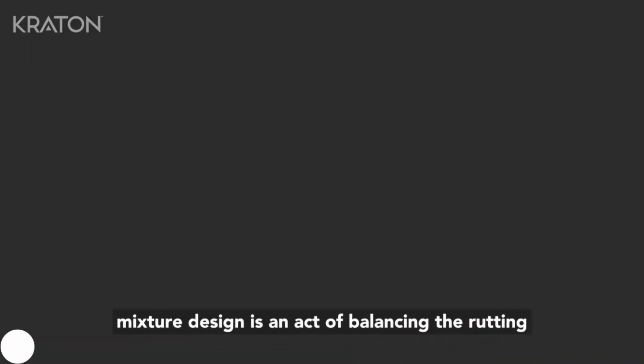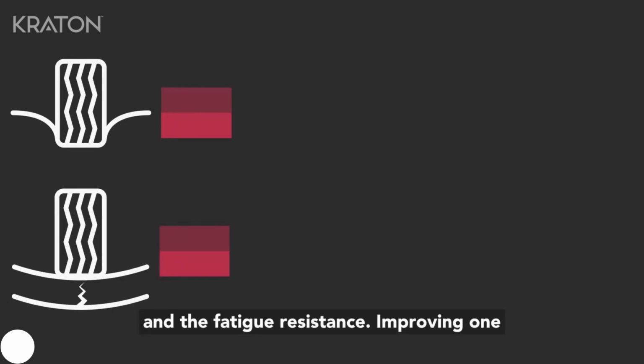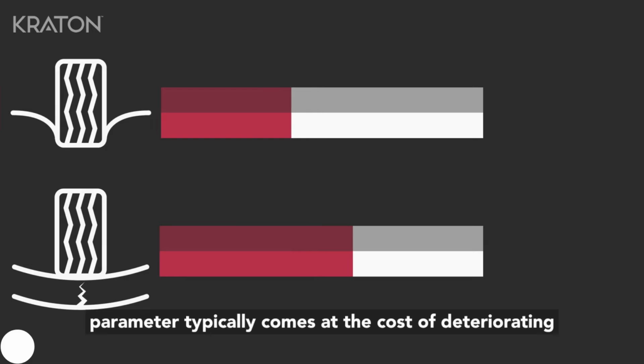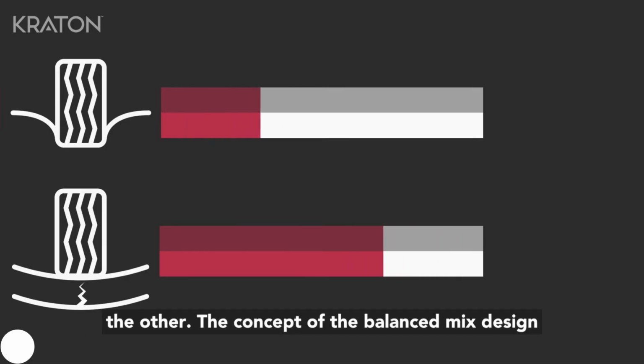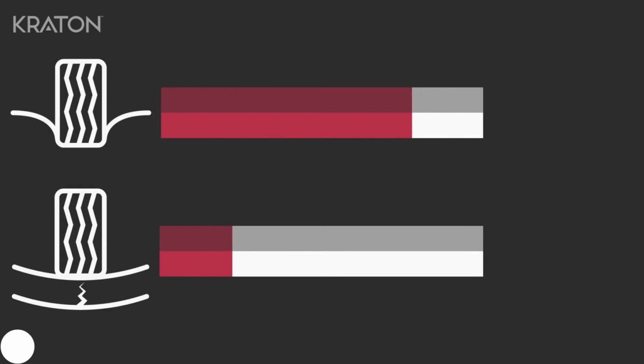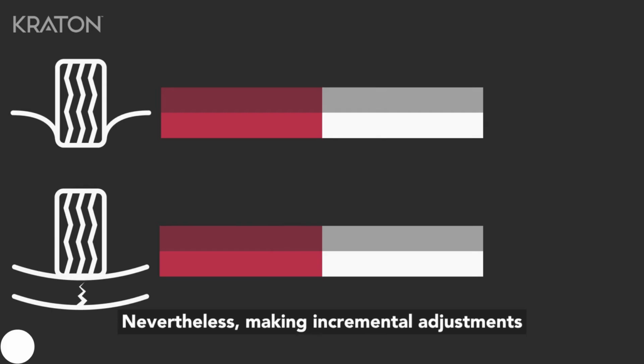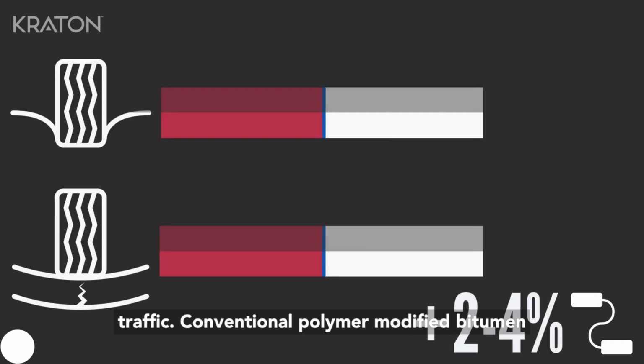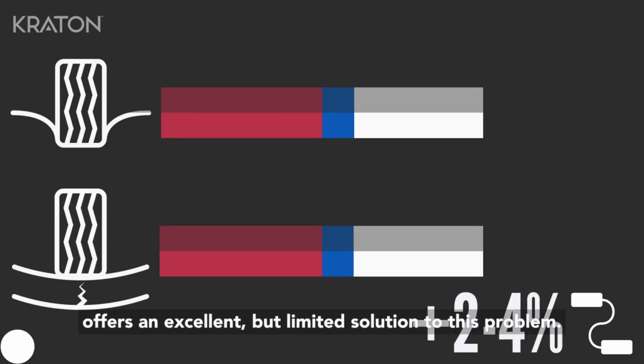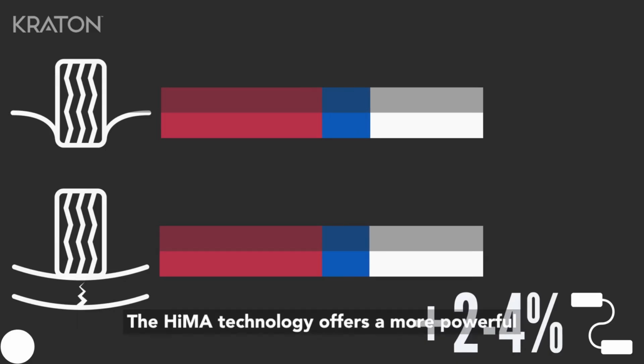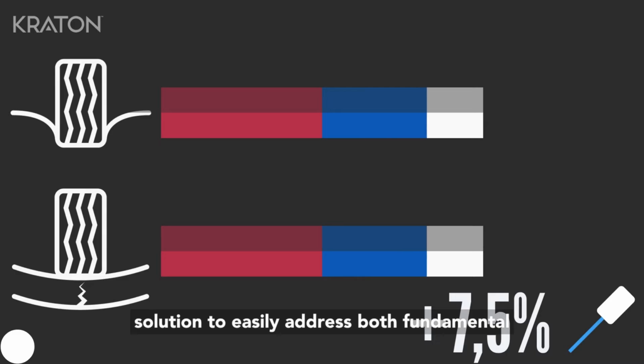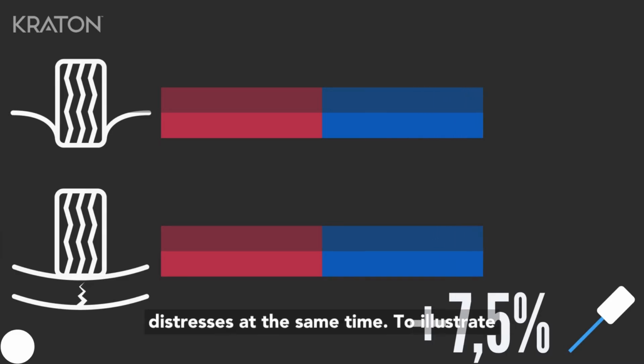Asphalt mixture design is an act of balancing the rutting and the fatigue resistance. Improving one parameter typically comes at the cost of deteriorating the other. The concept of the balance mix design may help to reach an appropriate balance. Nevertheless, making incremental adjustments to the aggregate gradation or the bitumen content has its limits, especially when the pavement structure must be thin or is subjected to a heavy traffic. Conventional polymer modified bitumen offers an excellent but limited solution to this problem. The HiMA technology offers a more powerful solution to easily address both fundamental distresses at the same time.